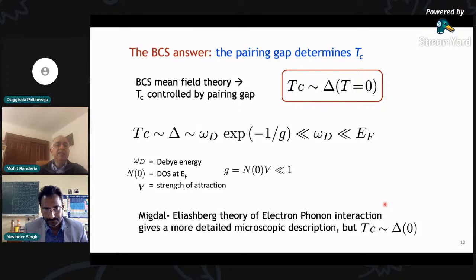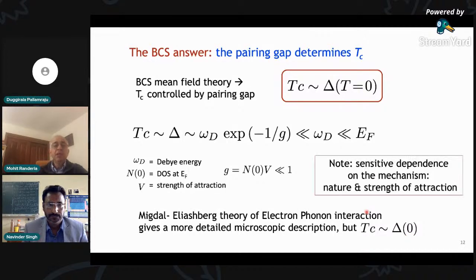And there are more detailed theories of superconductivity due to Migdal, Eliashberg, and others, which treat the electron-phonon interaction in much more detail. Okay, they give you answers which are quantitatively different from BCS theory, but qualitatively similar. TC still scales with the value of the energy gap at zero temperature. But the only thing I really want you to note from it, if you're not an expert, is that there's a sensitive dependence on the mechanism, the nature and strength of the attraction.